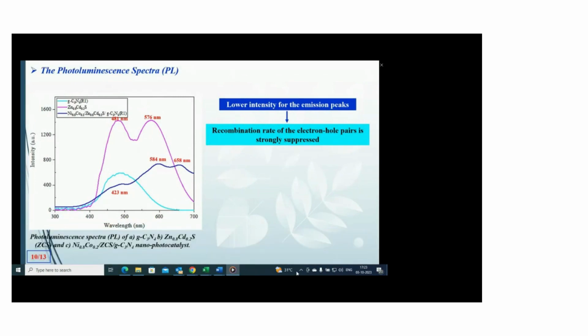This figure shows the PL spectra of the as-prepared samples. For ZnCdS, two PL emission peaks are observed in the figure, centered at 481 and 576 nanometers. These peaks can be attributed to zinc and sulfur vacancies, respectively. In the case of the ternary nanophotocatalyst, three broad emission peaks are observed, centered at 423, 584, and 658 nanometers. The lower PL intensity of the nanophotocatalyst compared to other samples suggests that the recombination rate of the photogenerated electron-hole pairs is significantly inhibited. This reduced recombination rate is beneficial for achieving efficient photocatalytic performance.